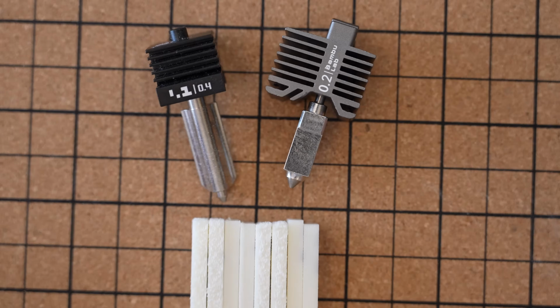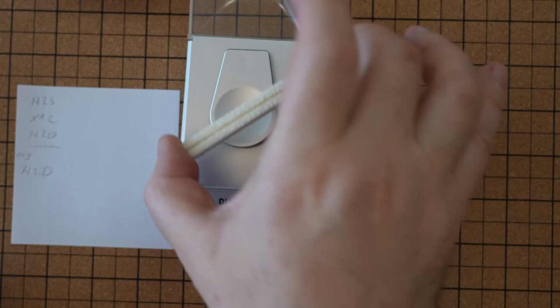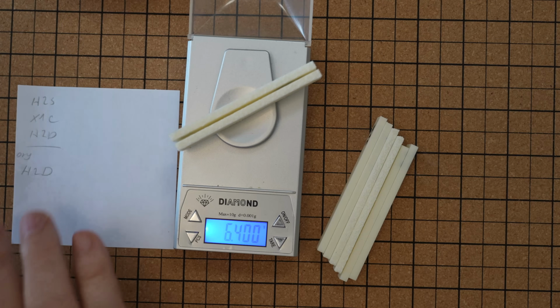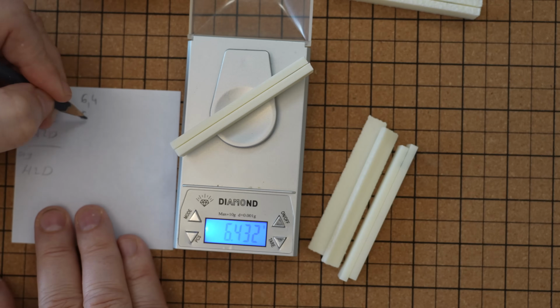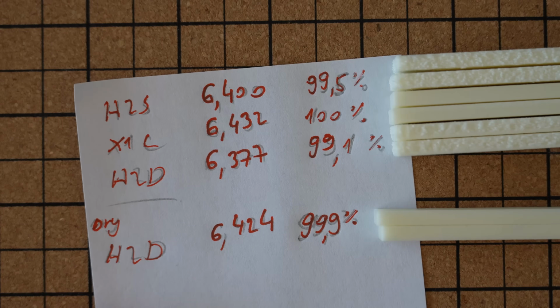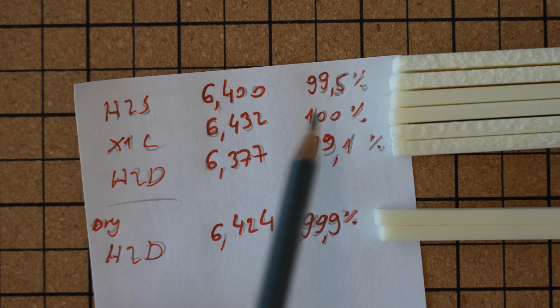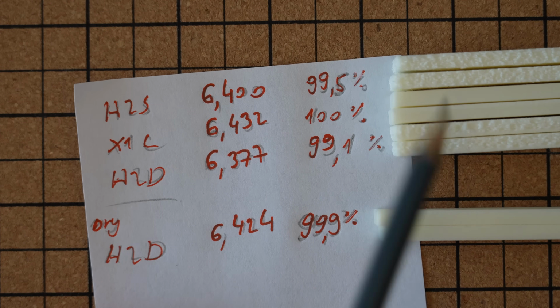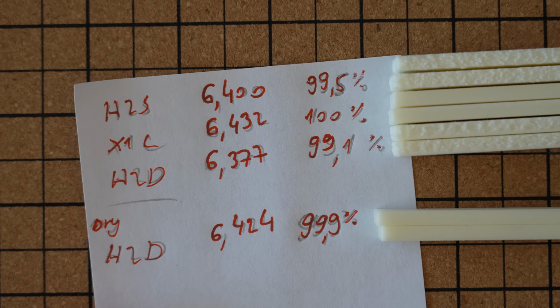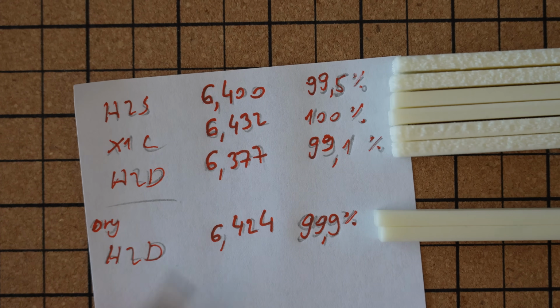Just quickly to measure the mass of the objects, this is H2S. After measuring the weight, I can see that these two are lighter a little bit, which is normal for this kind of porous filament. And interesting, on X1 Carbon before drying and H2D after drying, the weight is very similar. So definitely X1 Carbon handles this filament with moisture better.